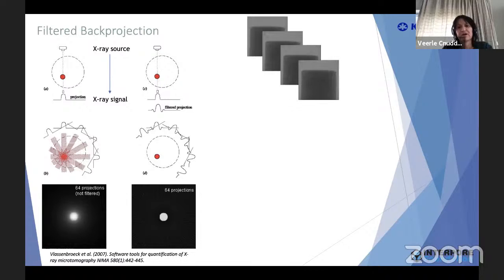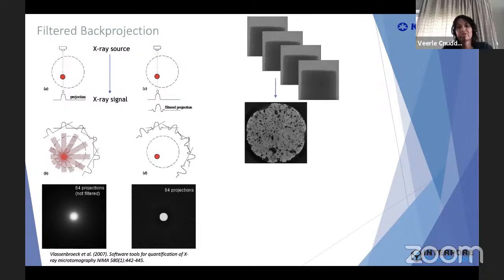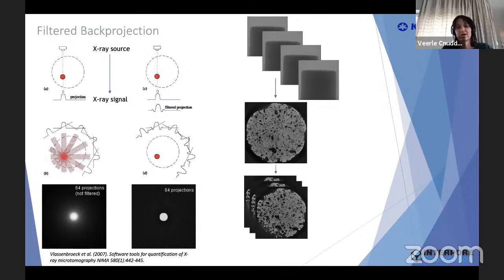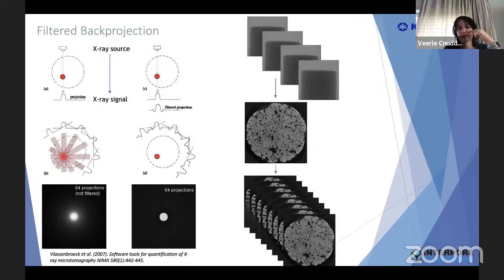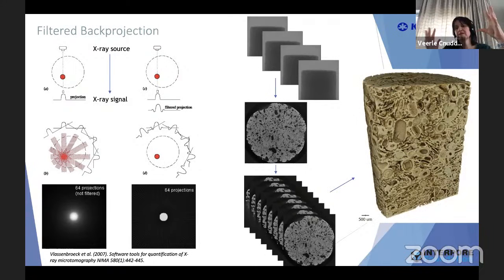So if you have a stone that you scan over different angles, your raw data is a series of radiographs. If you apply filter back projection, you are able to virtually reconstruct one slice, but in reality you have the entire volume scanned, so you can have all the slices of your sample. With X-ray CT, the resolution in X, Y, and Z is the same, and you can virtually render this volume into a 3D object. So after scanning, you have your virtual rock available at high resolution.